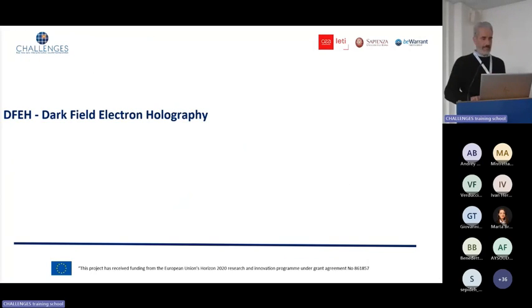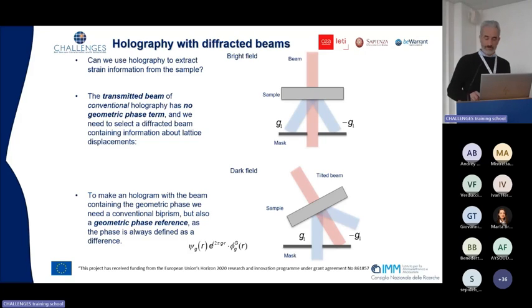Okay, quick to the final example. A very fascinating one. This is strain holography in the TEM. We can do the same things with holography, trying to do the same analysis in our materials, which are composed of undeformed lattices and deformed lattices. The variation in the strain, so in the lattice position, means a variation in the phase, and you can use the property of holography to detect this.